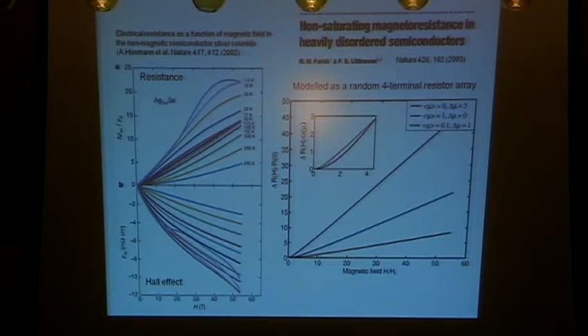If you take a two-component material, an inhomogeneous material, which is just an inhomogeneous semiconductor, and you treat it as an array of four-terminal resistors, and ask what does the magnetoresistance look like as a function of magnetic field, actually you get things that look like this. It doesn't saturate. The shape of these curves depends in detail on the mobility and the mobility fluctuations. It gets very linear as the material gets compensated, and that's one of the characteristics of this material. It has more or less equal numbers of electrons and holes in it. It is highly disordered, and you get curves like this.